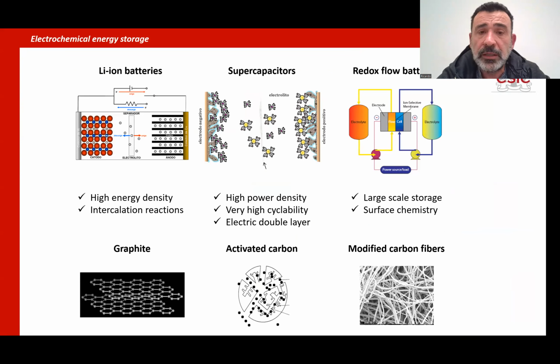of why different electrochemical systems have different carbon materials as electrodes. Lithium-ion batteries, we have seen we are using graphite because of the structure of the graphite, and we are working with intercalation of lithium inside the structure of the graphite. In supercapacitors, we use activated carbons because of the high surface area, and that gives us high power, very high cyclability. And the redox flow battery is a very good system for large scale storage.